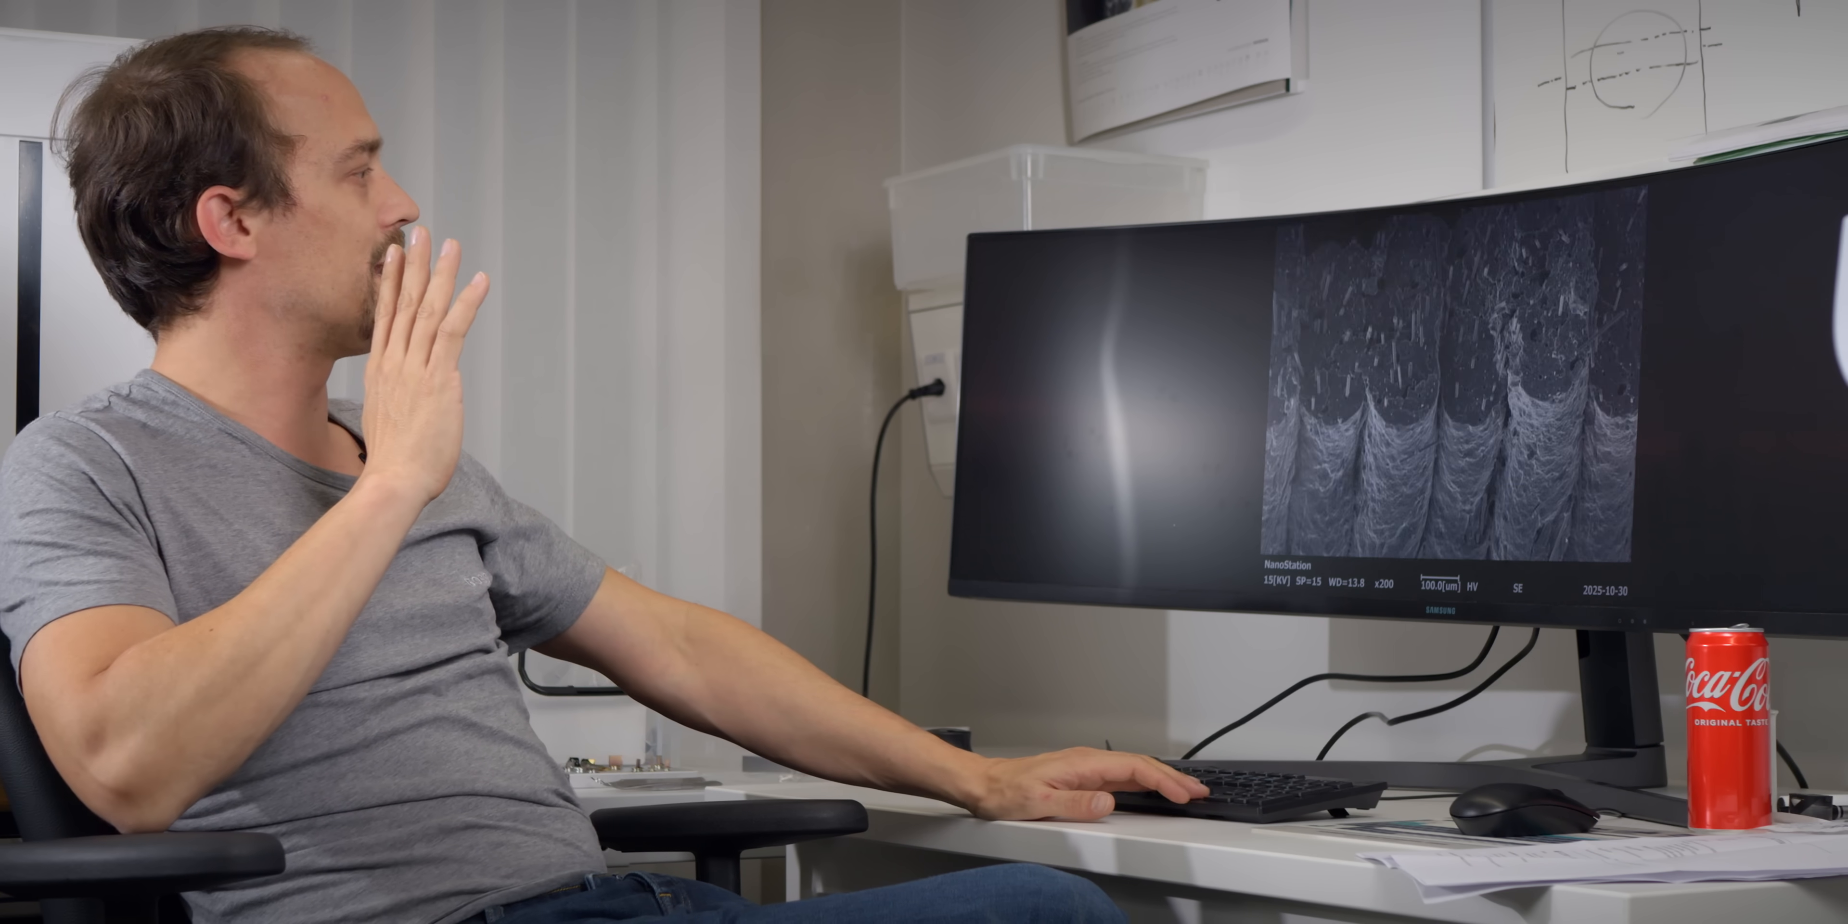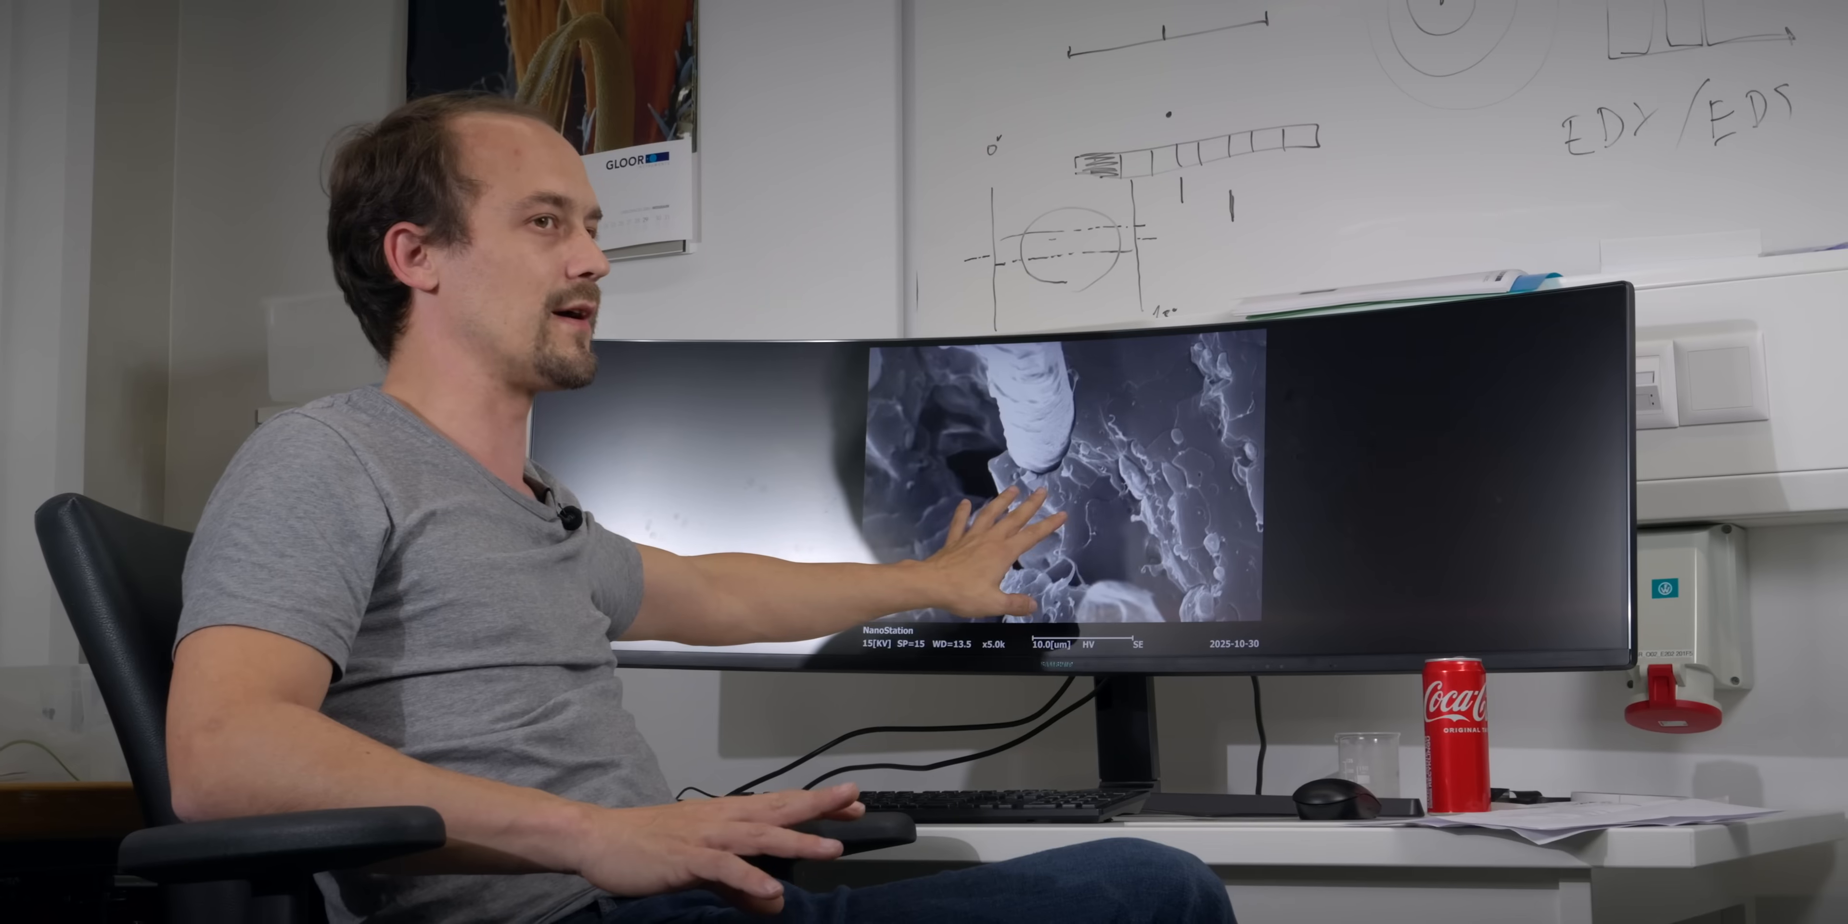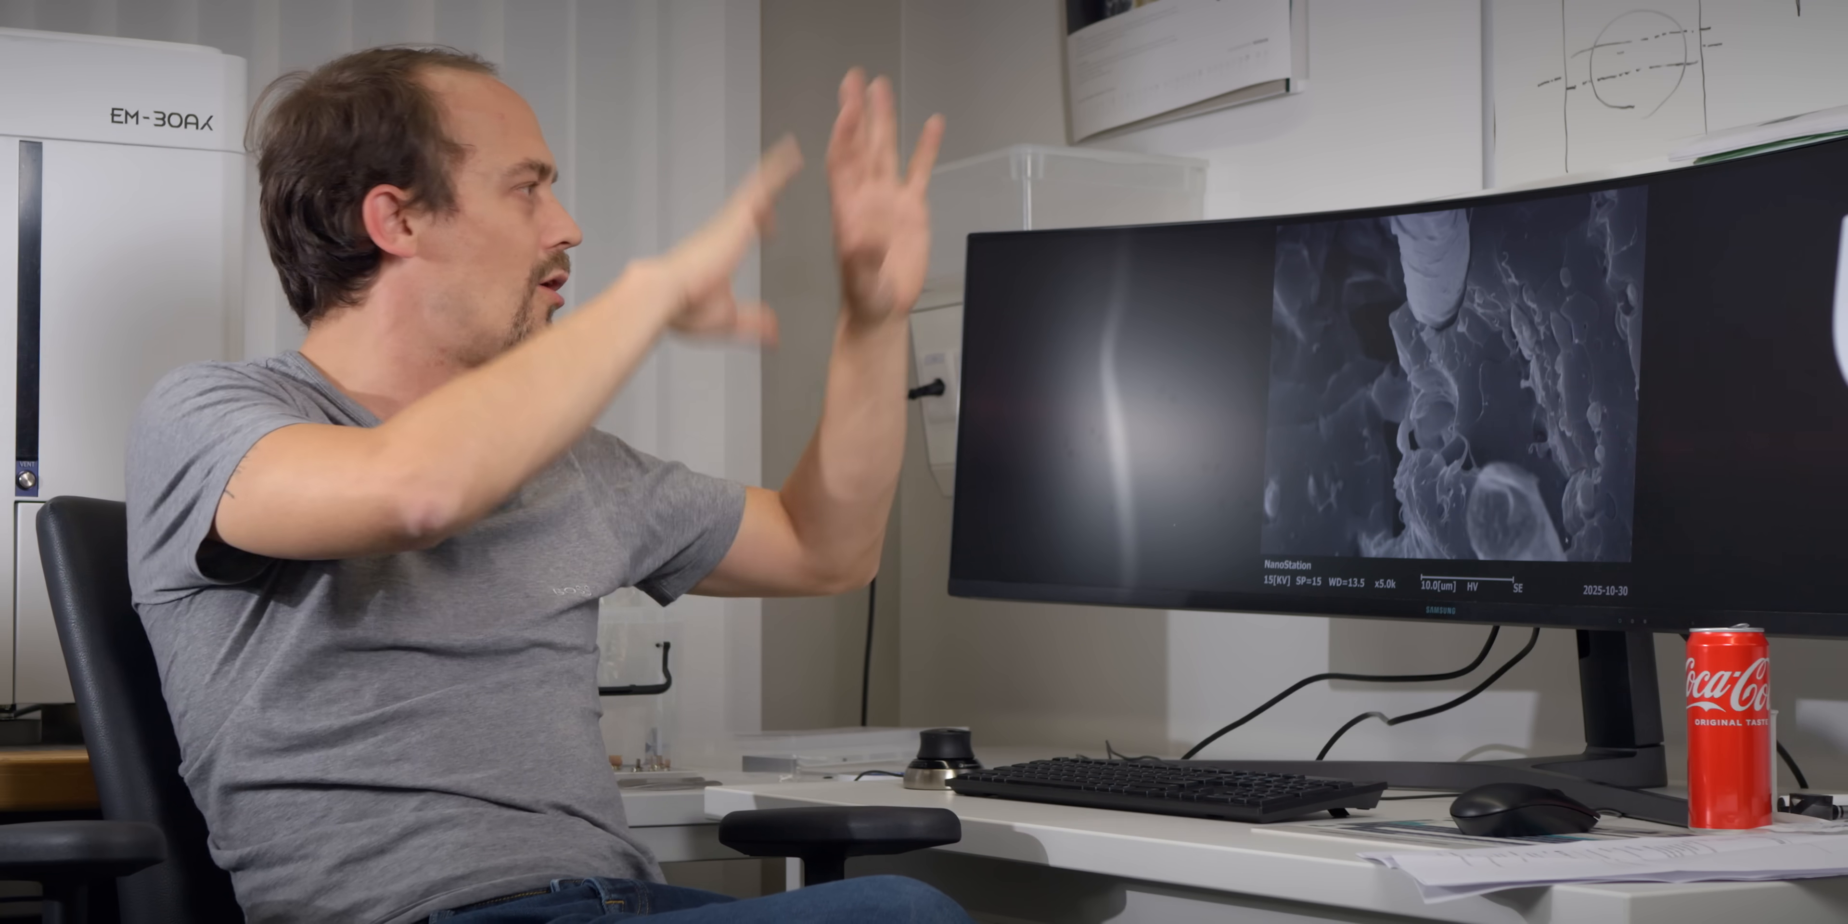Let me show you one other thing. If we zoom in to that area, which is exactly the line between two layers, and I go a little closer, you can see that here a carbon fiber was actually right in a layer boundary, and while breaking, I ripped it out completely. So you can still see the surface pattern of the carbon fiber there. But if you look at that carbon fiber, you see that the plastic actually does not adhere to the carbon fiber, and while cooling it just retracts from it. That could be the reason why carbon fiber reinforcement in PLA just does not add strength at all. This could be from me breaking the part because when I snap it, I could move the carbon fiber around and disturb the polymer around it. Even though I saw it all over the place in that sample.